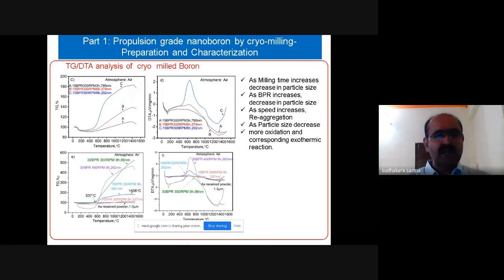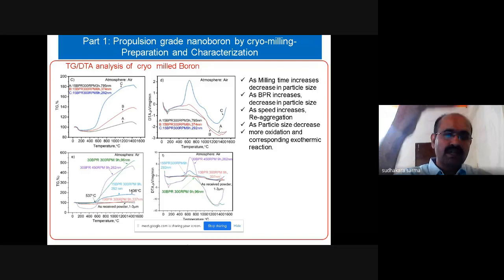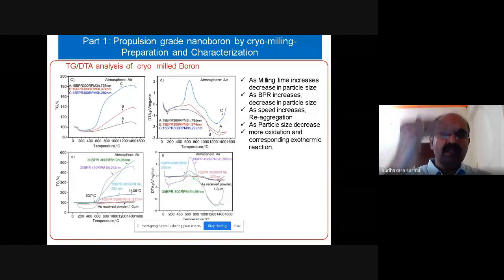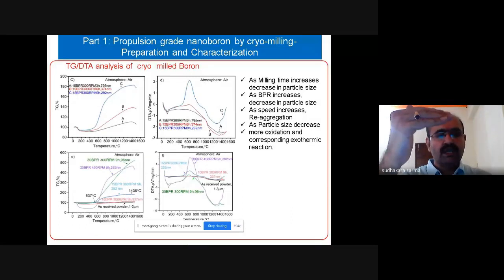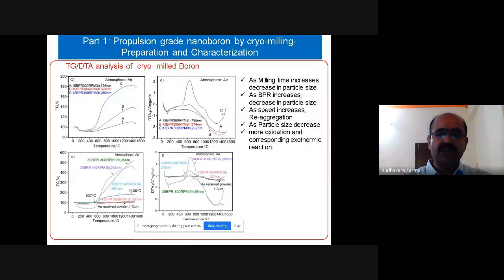Similarly, we can see the TG curves for as received powder, that is 1 to 3 micron size powder, that is powder before milling, and after milling at 10 BPR, 15 BPR and 300 rpm, 30 BPR, 300 rpm, 30 BPR, 450 rpm. So with increasing BPR, particle size is coming down and mass gain is happening. That means more oxidation. If we see the corresponding DTA curves, we can see the exothermic reactions at the corresponding temperatures.